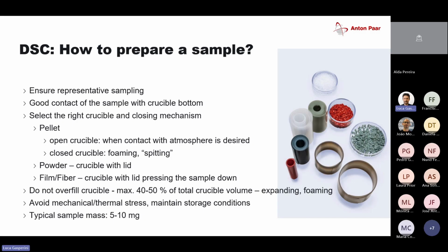And what should be the typical mass? I would say for polymers, 5 to 10, maybe 15 milligrams is usually good enough. So you don't really need much of a sample. You'll see in the afternoon how the sample actually looks and how it sits in the crucible. And this is something that we can discuss also at that point.